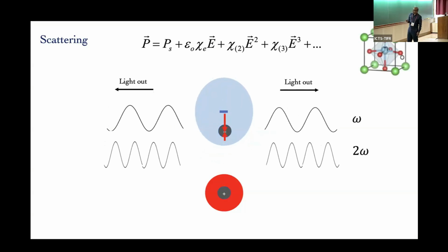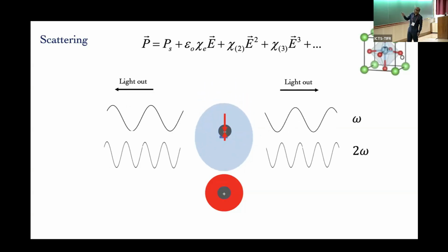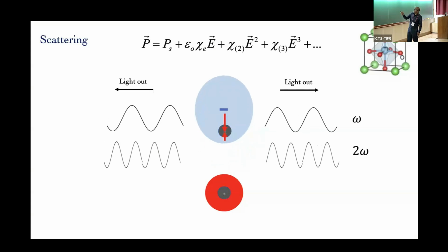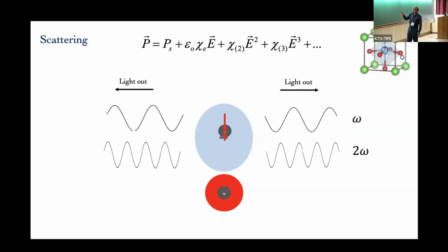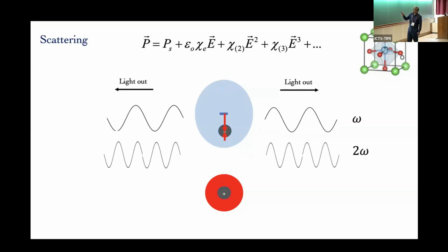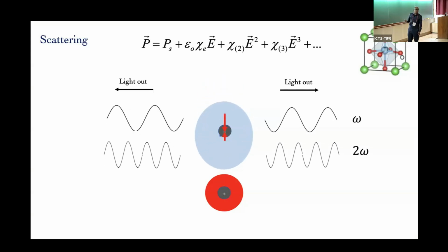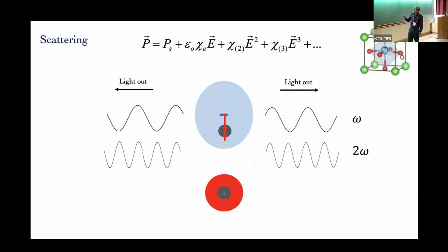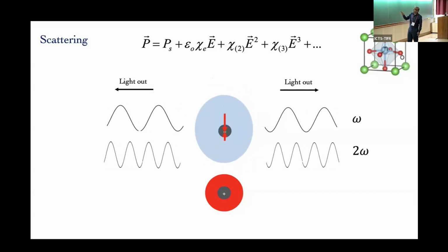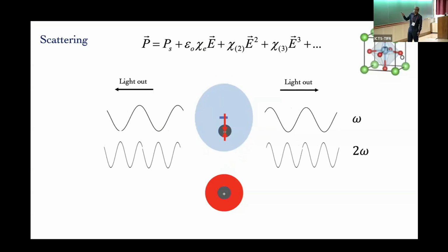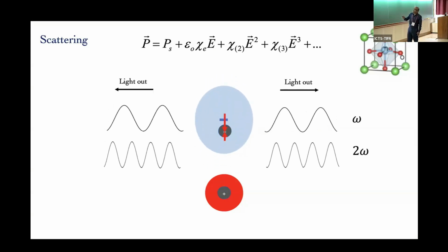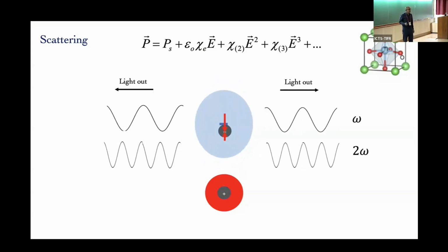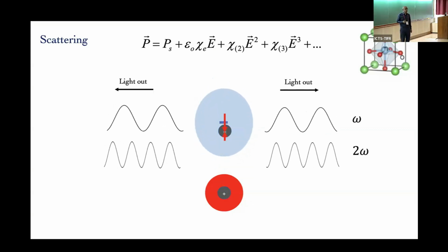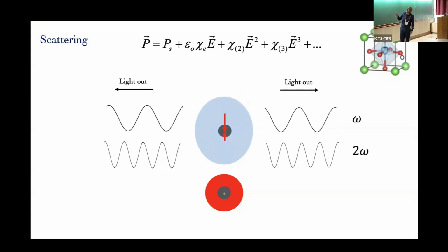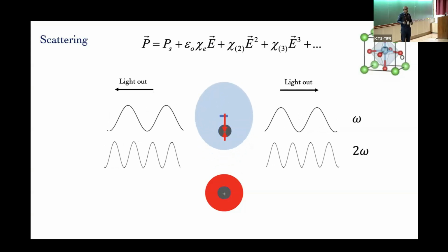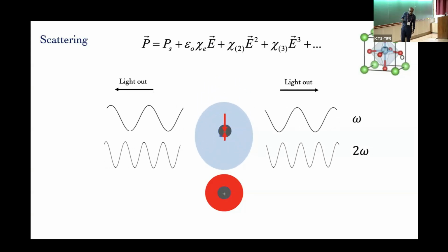Okay, so I'm going to talk about ferroelectrics, which turns out, here, for example, barium in the corners, oxygen forms an octahedron. There's a titanium in the middle, and this titanium at lower temperatures pops up a little bit. See, it's not in the exact center of this. So the center of positive charge is slightly to the top compared to the negative charge of the oxygen atoms. So this is a frozen polarization, right? Frozen dipole moment for a unit cell. And that can be sloshed back and forth. The titanium can move back and forth by applying electric field. That's called a ferroelectric. So we are going to look at that.